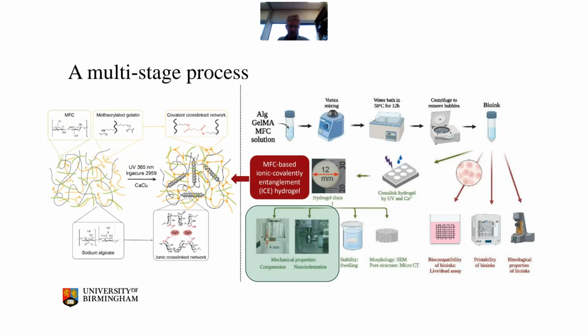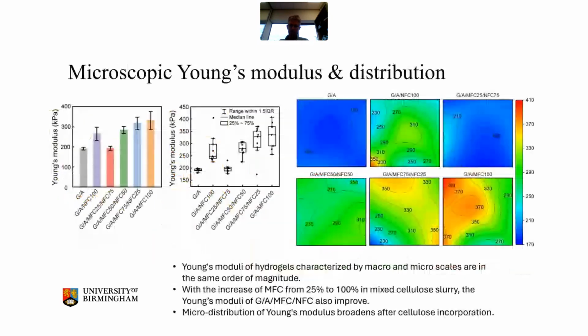You can see that structure there, and his group, as part of this multi-phase study, looked at the mechanical compression, but also the small-scale mechanical properties, to have a better understanding of the subtleties of the process. What they found, in agreement with macroscale compression data, is that putting nanofibrillated cellulose or microfibrillated cellulose in increases the stiffness of the composite. It also changes the distribution a little bit, but it's somewhere in between, and it's less successful. So it's interesting to find out why, and we can dig behind that a little bit.